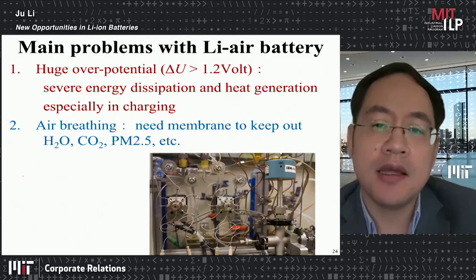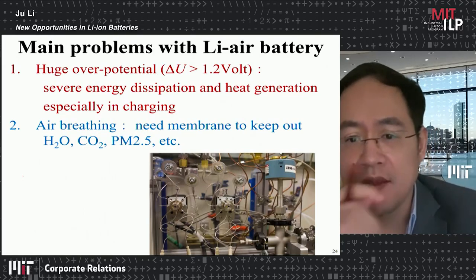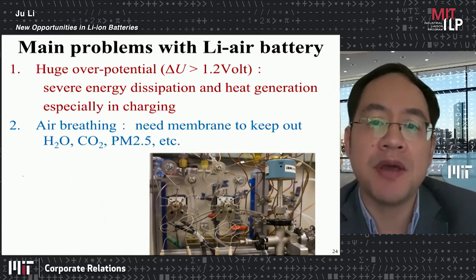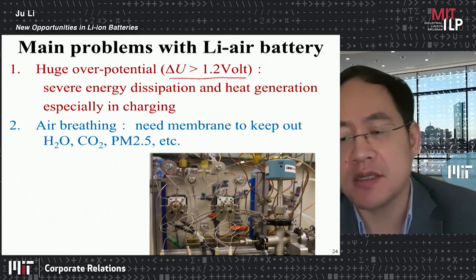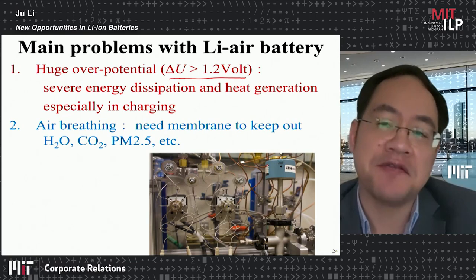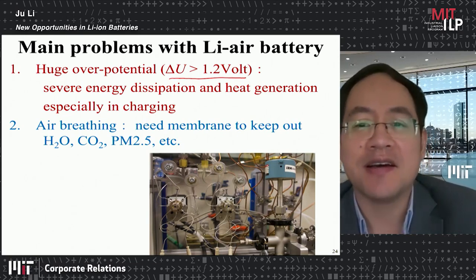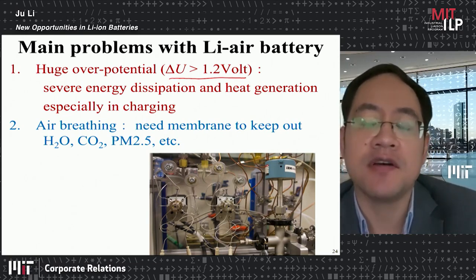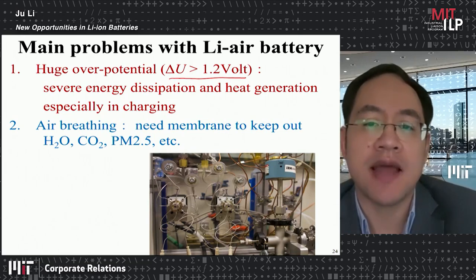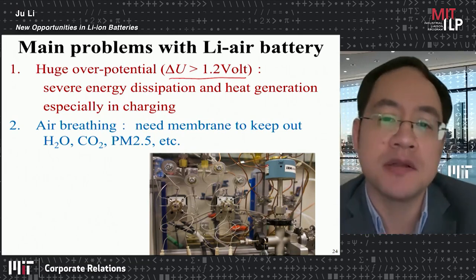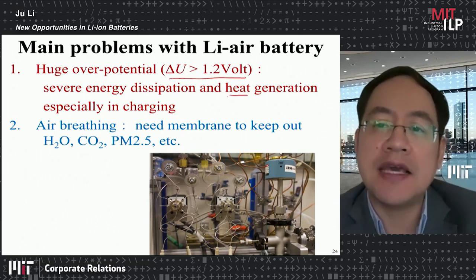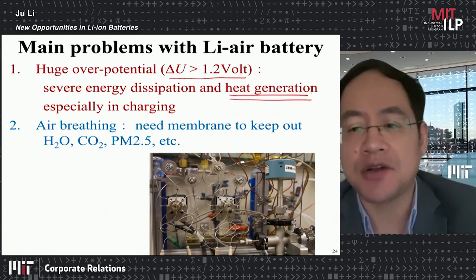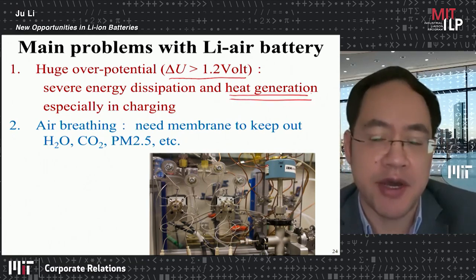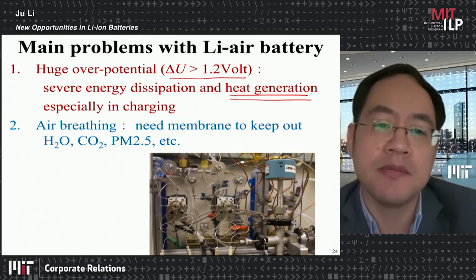And in lithium air battery, for example, we have this big overpotential, and the reason for this overpotential is you have phase transformation from condensed matter to gas phase. And that involves a huge density difference and a hysteresis in the phase transformation. And that generates a lot of heat, which actually limits your charging rate, for example. That's a very practical problem.